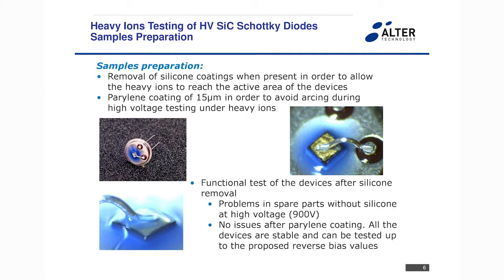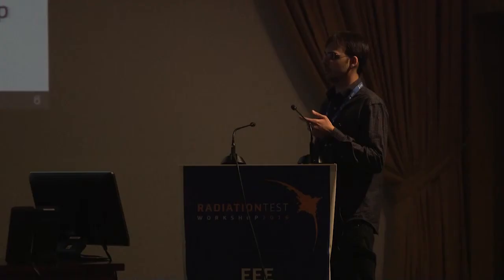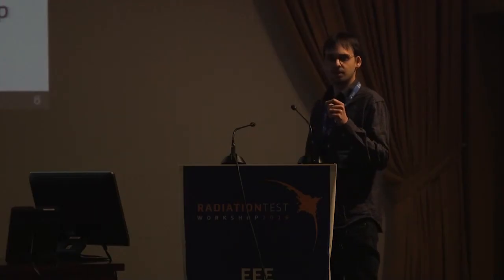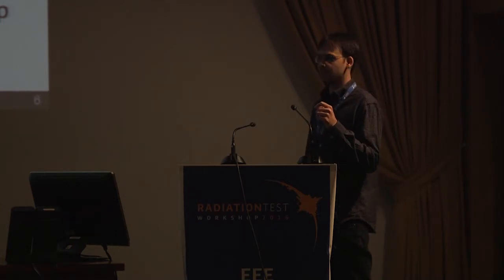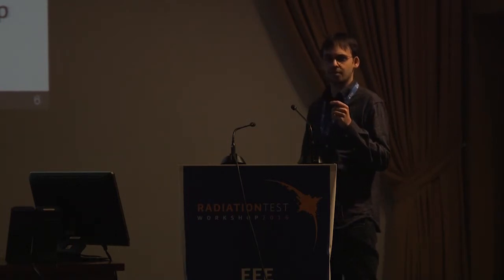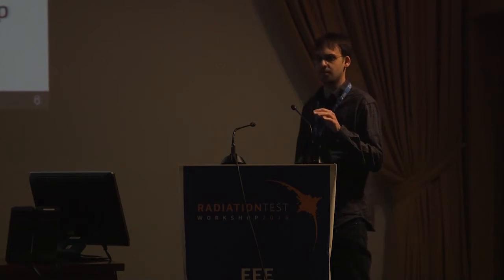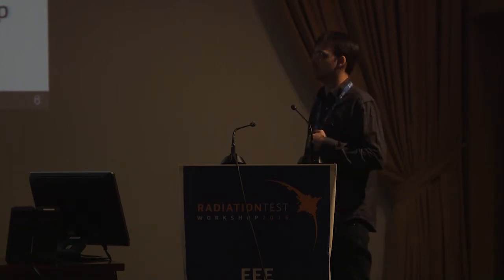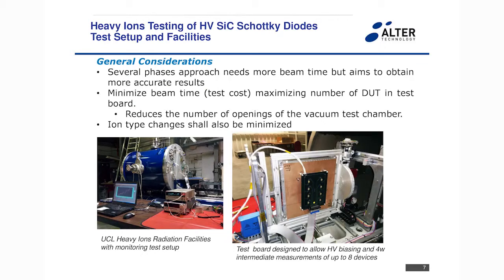So we use a parylene C coating of the devices. You can grow a parylene coating of 15 microns, and this very thin coating allows the heavy ions to reach the active area of the device and completely solve the problem of the discharges. Well, you have to check the devices before and after the parylene coating in order to ensure everything is stable before the test.